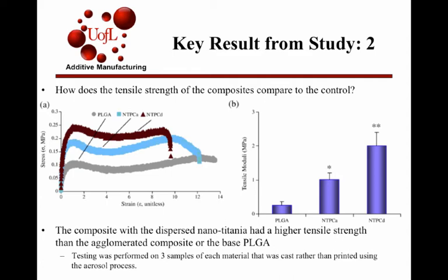The second study that we'll look at is how does the tensile strength of the composites compare to the controls. Like I said, they didn't do 3D printed samples, they cast some tensile bars and tested them on the Instron. You can see on the right the numbers for tensile modulus. The dispersed nanoparticles had a far better structural strength, and their stress-strain curves are on the left there. The control PLGA is not weak, but it could be stronger, especially for bone grafts. And that was the goal, to mix in these nanoparticles. The dispersed had a more uniform structure, and it was a better performance. So the composite with the dispersed nanotitania had higher tensile strength than the agglomerated or the base PLGA.